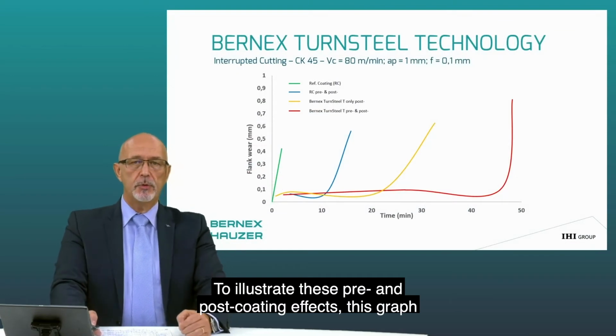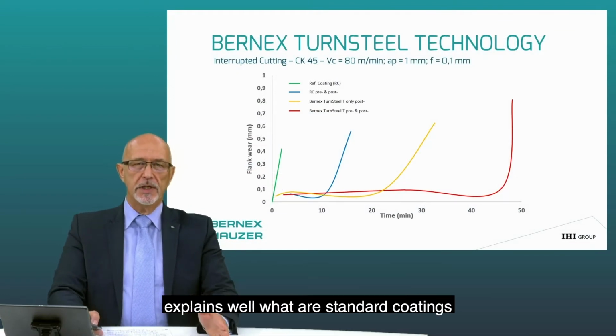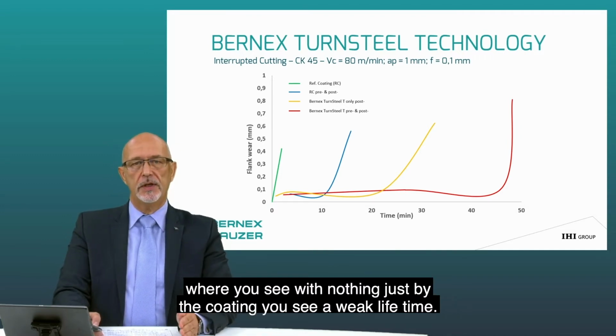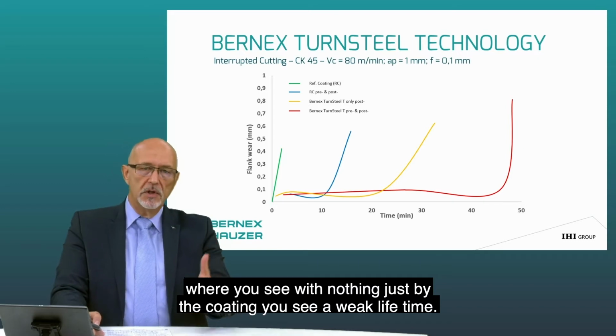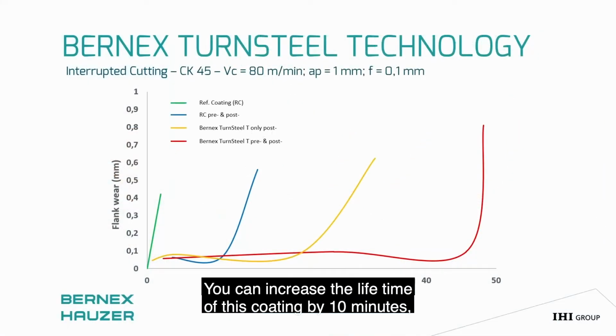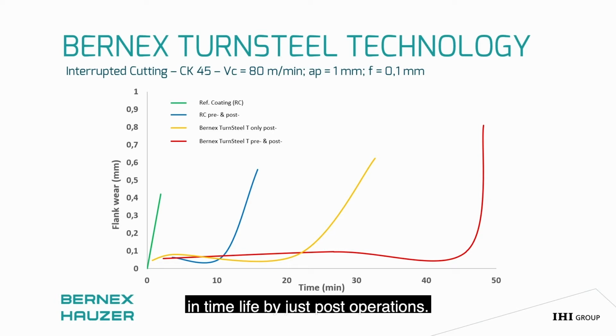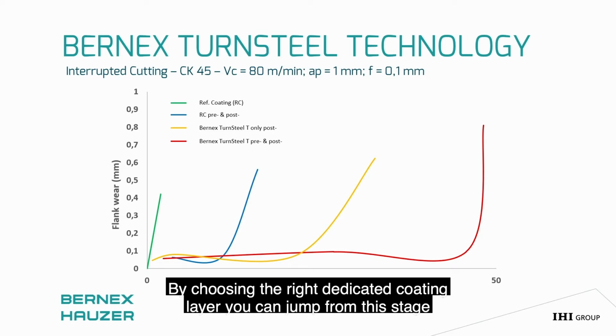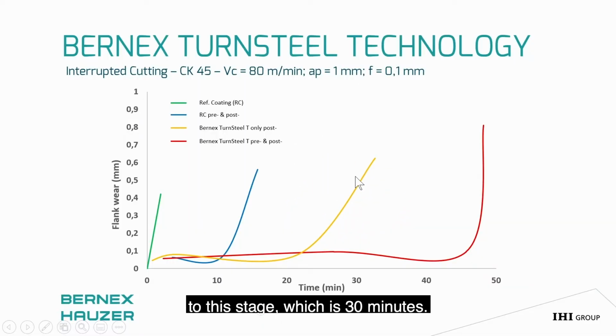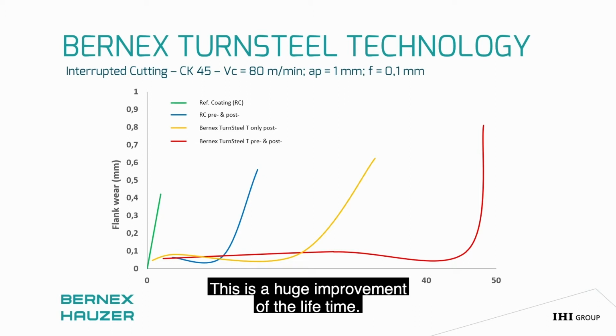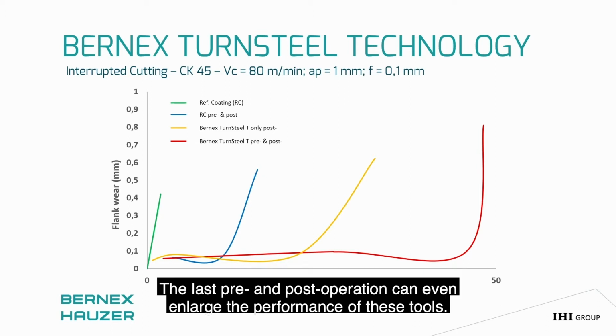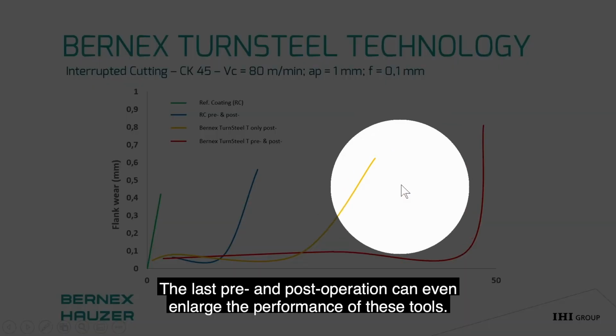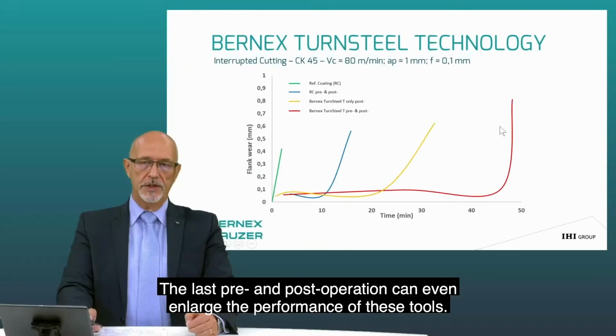To illustrate these pre and post coating effects, this graph explains well what happens with standard coatings. You see that with nothing, just the coating, you have a weak tool life, and you can increase the tool life of this coating by 10 minutes just by post operations. By choosing the right dedicated coating, multi-layer, aluminum oxide and texture, you can then jump from this stage to this stage, which is 30 minutes, a huge improvement of tool life. And the pre and post operations can enlarge the performance of these tools even more.